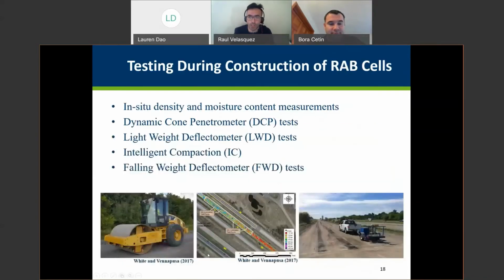So now let's switch gears a little bit. Let's move, as Bora mentioned, into the field performance at MnROAD. Before and during construction, we performed extensive testing of these recycled aggregate base cells, which included in situ density and moisture content measurements using traditional methods like the nuclear gauge, spot testing, and sample collection. We also did DCP testing for shear strength and stiffness estimation, lightweight deflectometer testing, intelligent compaction by Ingios, David White, and falling weight deflectometer tests as well.